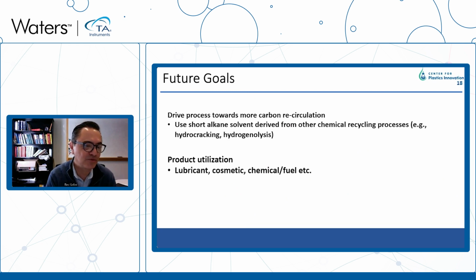As I mentioned, some of the members of the center here at Delaware investigate the hydrogenolysis of hydrocarbons, and in this particular case, they produce mixtures of hydrocarbons that have suitable molecular weights for what we want to do. And so we can envision now sort of a refinery for the processing of plastics in which we use some hydrogen to break down the polymer and make a liquid, and then we take that liquid and mix it to this molecular redistribution process with new polymer, such that the total amount of carbon that comes into the refinery is pretty much the amount of carbon that comes out as a product, favoring the circularity of the process overall.